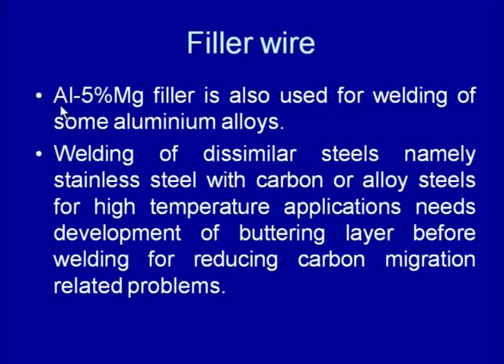So, in addition to the aluminum silicon filler materials, for aluminum welding we also use the aluminum magnesium filler materials, but these are found suitable under certain conditions only, because in other conditions they lead to solidification cracking. For example, aluminum 5% magnesium filler material is also used for welding some aluminum alloys.